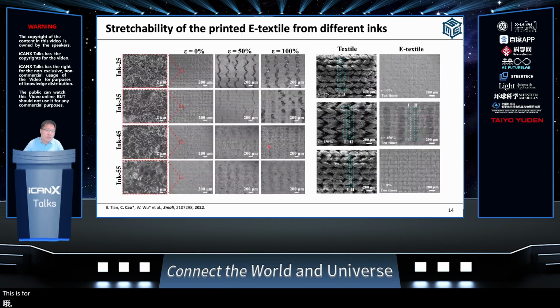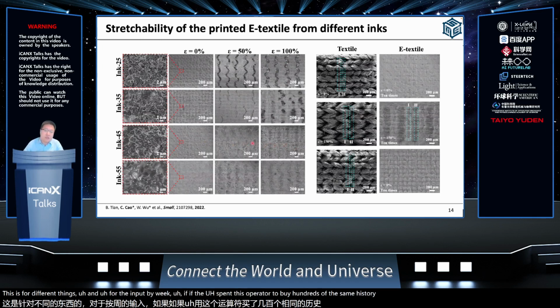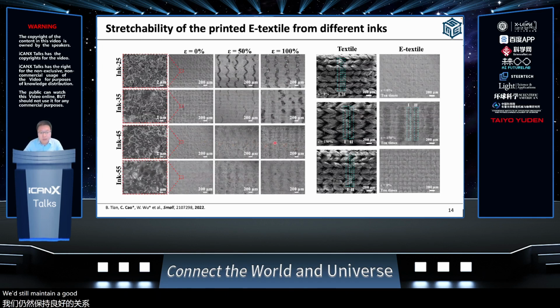These are 4 different inks, and for ink 45, we stretched the substrate to 100% strain. It still maintained a good intact state. The deformation mainly comes from the gap regions on the surface, and you can see it forms some wrinkles here.